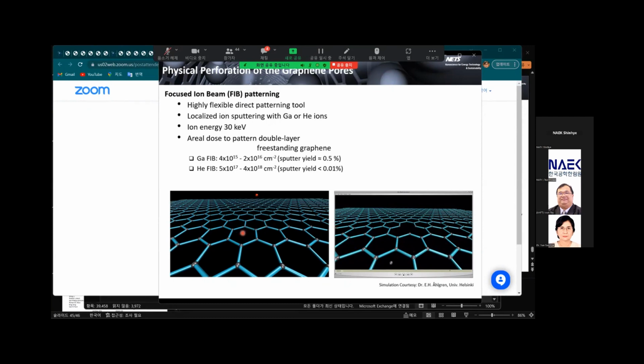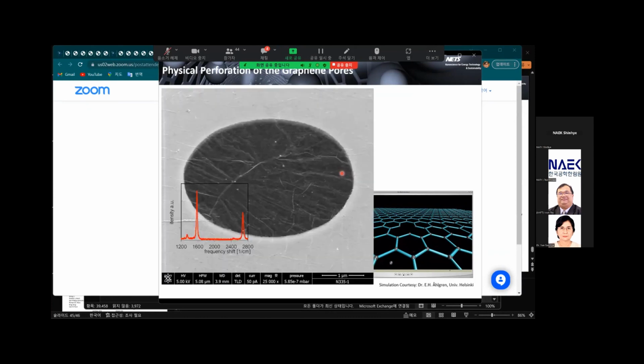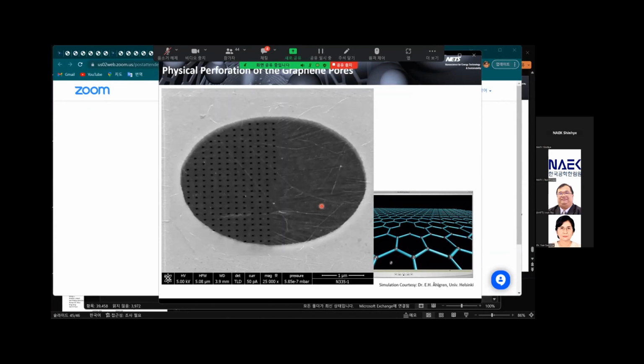But if ions somehow miss carbon atoms on the left, the ions can just penetrate graphene without stripping off any atom. This simple mechanism may explain why the sputter yield for the perforation process can be very small. Anyway, in this mechanism, focused ion beam milling can perforate pores one by one on a freestanding graphene layer.